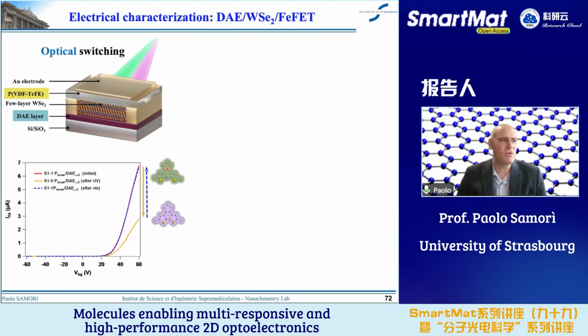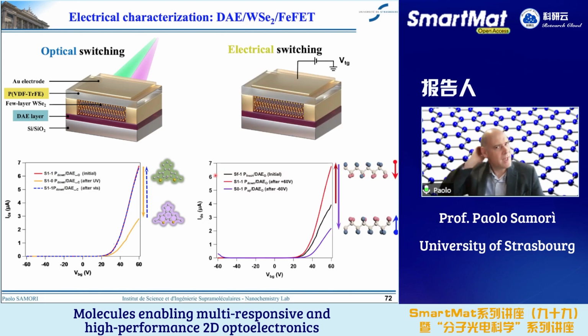First of all, I wanted to prove that we can still switch the current through the tungsten diselenide with light stimulus by changing the state of the diarylethene, because in this case we placed diarylethene underneath, and so that was not obvious. It did work. But you can see here that we can actually change the state of the diarylethene from the open with higher currents to the closed, and vice versa. And so then on the right, I will show you how you can have the electrical control over the switching.